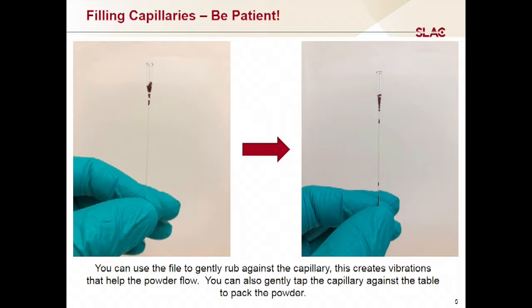What you want to end up with is a good powder bed at the bottom of the capillary that is as packed and as dense as you can make it. So by tapping it, you kind of pack it down. What you're going to end up with, even for a well-packed capillary, is about a 60% filling. So if you know the density of your material, you're only going to get about a 60% density in that packed powder bed. That's just kind of the nature of how random packing works.